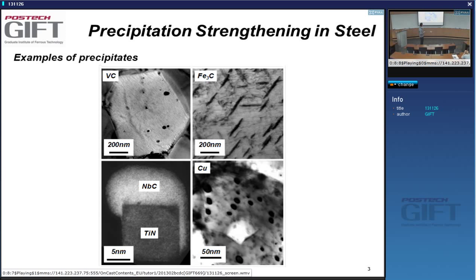And you can see indirectly that the cementite is coherent with the ferrite lattice because it's got this needle shape, and you can see the needles are either at somewhere 70 or 80 degree angle or horizontal, right? So that tells you there is a high degree of coherency. There's going to be a lattice correspondence, an orientation relationship, between the cementite and the matrix.